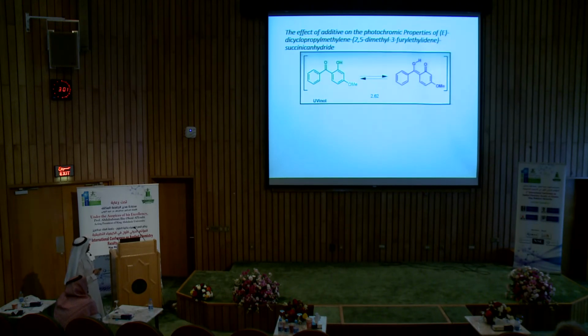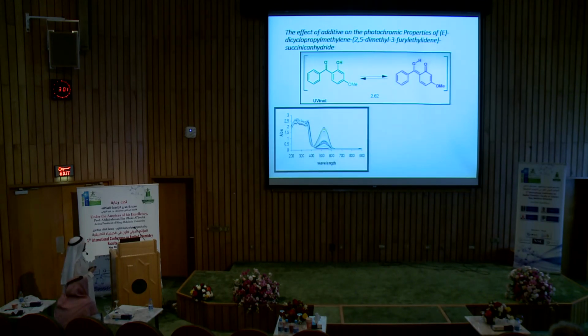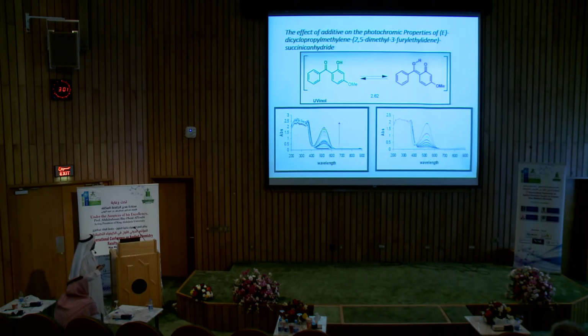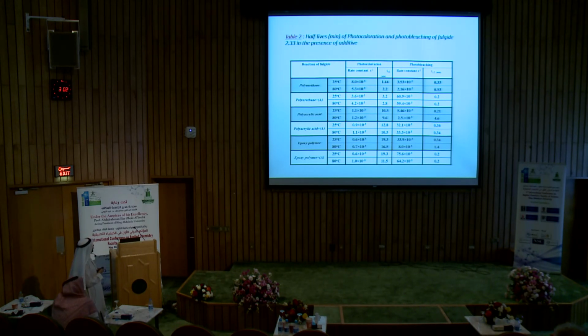So we used this Uvinul, which is a commercially available UV absorber used in the polymeric industry. And this is the photocoloration in the presence of this Uvinul. And this is the discoloration. And let us see the fatigue. This is the half-life table and the rate constants for this photocoloration and discoloration process at different temperatures in different polymeric matrices, in the presence and the absence of UV absorber.